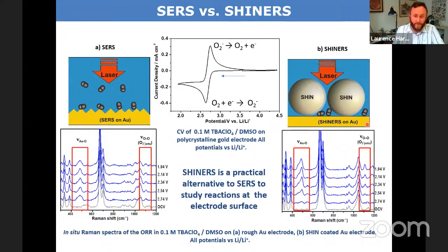And we've repeated this again on planar gold and also many other different substrates, and seen the superoxide form. So we have this oxygen stretch of our superoxide, and we see this grow as the potential increases.